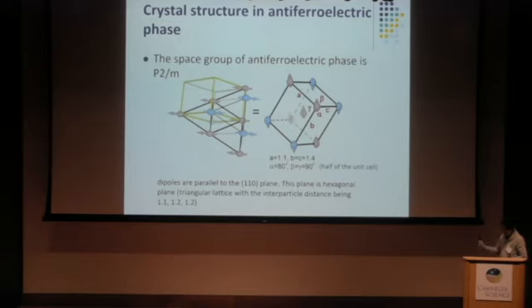For the paraelectric and ferroelectric phases, the hexagonal plane is the closest packing in two dimensions, and the stacking of hexagonal planes is the closest packing in three dimensions. But in the antiferroelectric phase, the stacking is different from both the ferroelectric and paraelectric phases. So it's not a standard ABC or ABAB packing to yield FCC or HCP. The position of the anti-parallel dipole moment is at the midpoint of the adjacent plane.